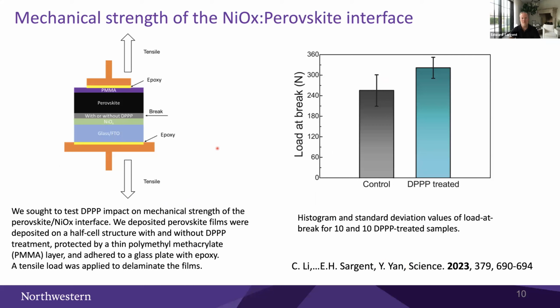He saw evidence of increased mechanical strength resulting from improving the control over this interface. You see on the right that when Chong-Wen and his colleagues developed a test for delamination, they found a higher load at break when they did the DPP treatment. I'll just emphasize that the final author on this is Professor Yanfa Yan at University of Toledo. Chong-Wen did the bulk of the origination of this work while he was working with Yanfa, and then he continued and completed the project in our group.